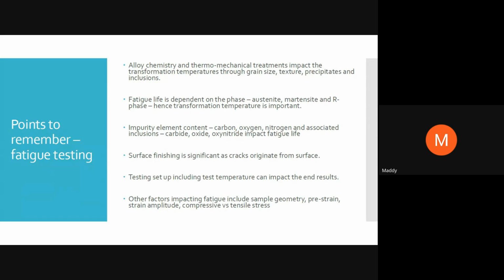So there are a lot of factors. There's an article by Shaw and Kyriakides which details how these factors are extremely critical and important in getting good and credible results. Other factors include the sample geometry, like what I mentioned, a diamond-shaped sample being used in the industry in general, and then you have the strain amplitude, the pre-strain put into this, as well as the distribution of compressive versus tensile stresses. All these things impact your fatigue characteristics. These are not comprehensive, but at least some of the key points that one needs to remember when it comes to understanding the fatigue of these alloys. Next slide, please.